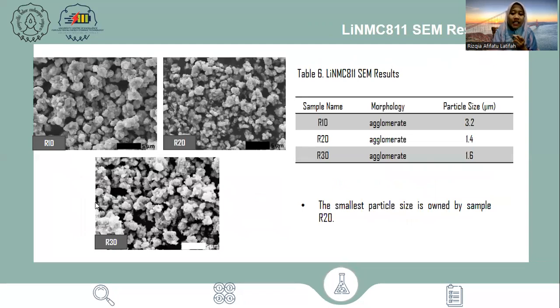The next is the result of characterization using scanning electron microscope. The resulting particles have agglomerated shapes with sizes that are not homogeneous. Primary and secondary particles have been formed, and the smallest particle size is owned by the sample with the variation of 20 g/L.